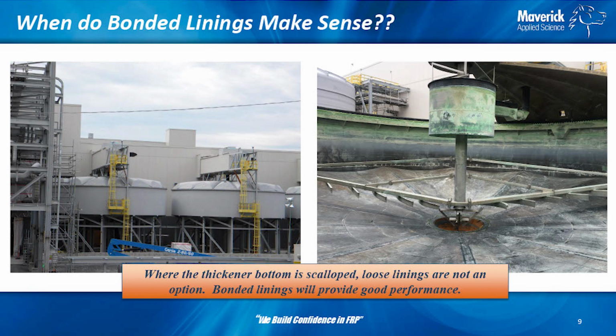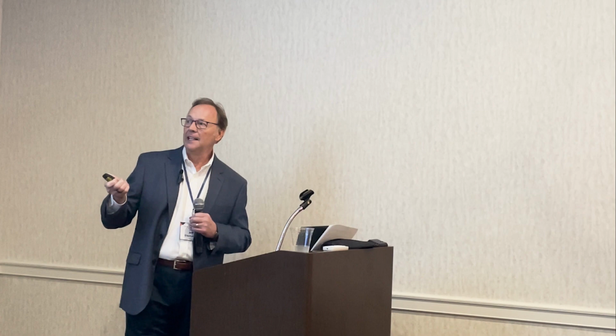So this was actually rubber lining after around 10 years or so, and they're starting to have some edges peel up and things like that. So this is where we would basically blast out the lining and then get our surface profile. Probably it's going to be covered, and we're going to put a primer down so we can get a bond to the surface. We have primers that literally will bond to almost anything. We can bond to concrete, we can bond to stainless, we can bond to carbon steel, and they work great as long as we follow the rules. And then we're going on with an FRP structural lining after that.